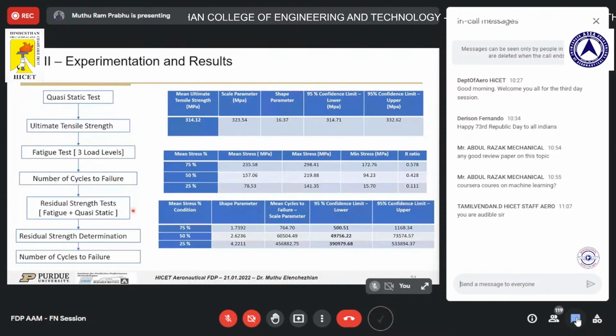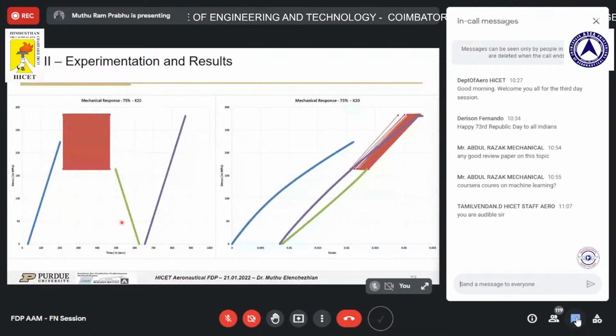And after that, I did some more tests to identify the residual strength, that is, the remaining strength of the material. So this is a typical pattern that we used for the fatigue test, where we load up to a certain level and do fatigue for a limited number of cycles and then ramp it down. And after the cycles have been done, we pull it up till failure to know the actual remaining load of the material.